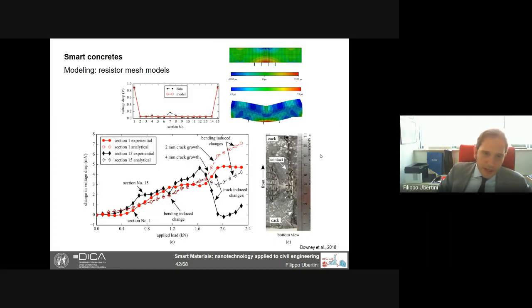If you recall the experiment on the beam, where we saw this sudden change in voltage drop across section 15 and section 1, when there was a shear crack forming out of the electrodes. Here you see a comparison between experiments and numerical simulation. So you have to compare the continuous lines, black and red, that are experimental, with the analytical predictions that are also black and red, but they are dashed.